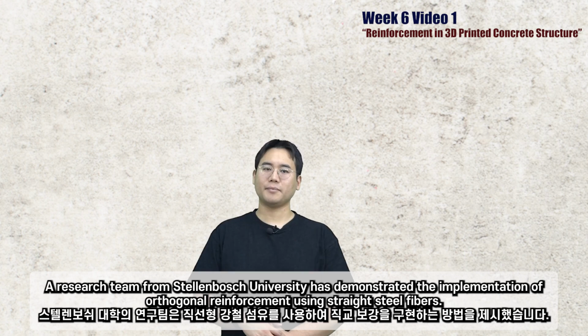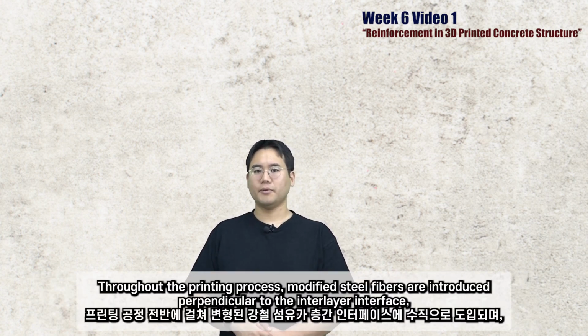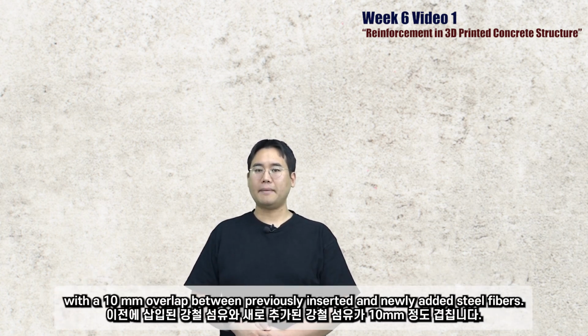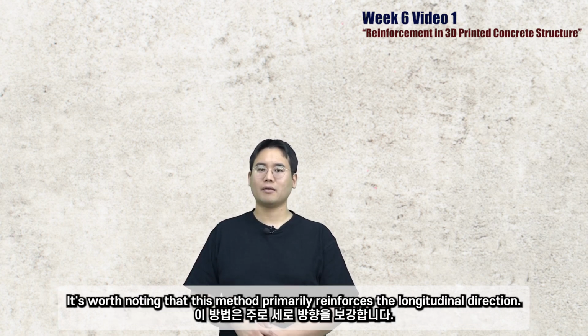A research team from Stellenbosch University has demonstrated the implementation of orthogonal reinforcement using straight steel fibers. Throughout the printing process, modified steel fibers are introduced perpendicular to the interlayer interface with a 10 mm overlap between previously inserted and newly added steel fibers. Worth noting that this method primarily reinforces the longitudinal direction.